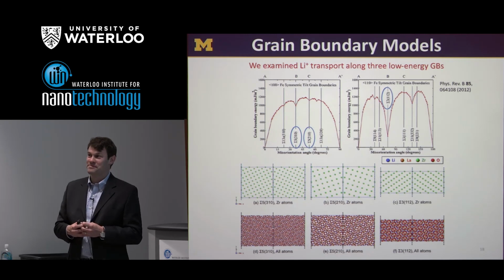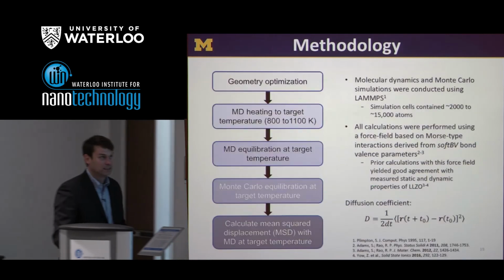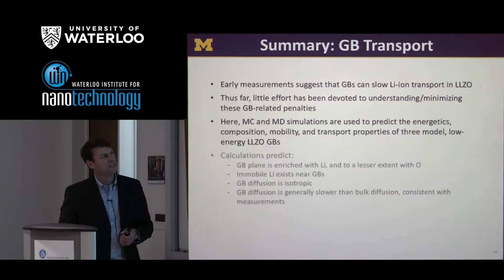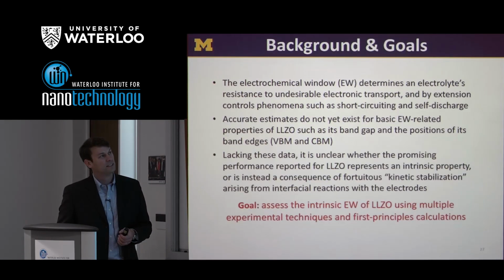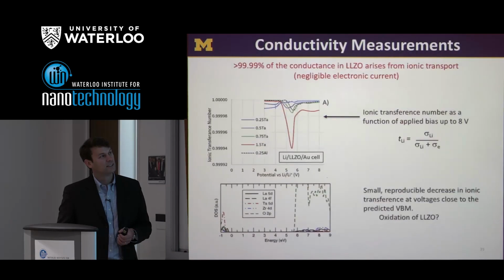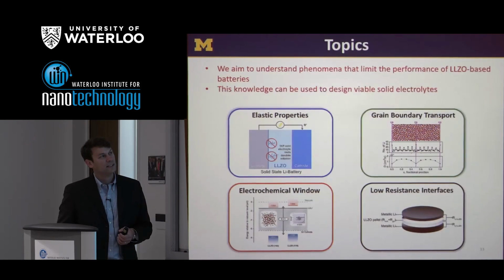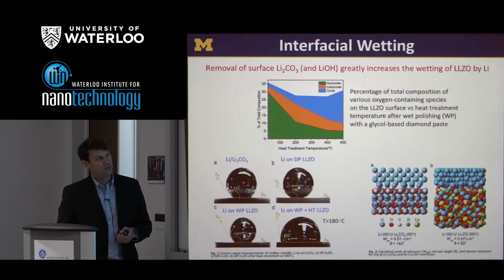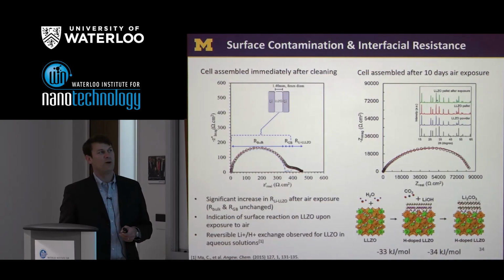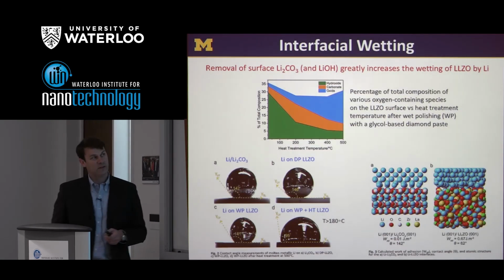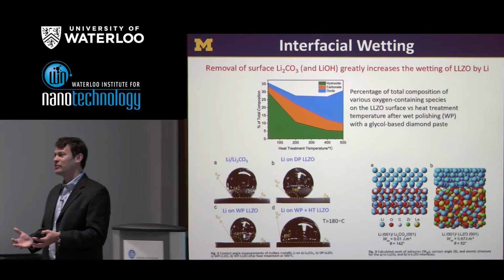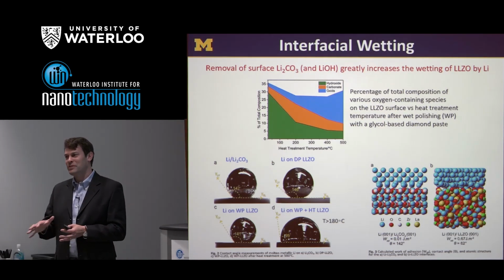About the wet polishing and heating treatment. Question about heat treatment: do you need to heat it under a protective gas atmosphere or just in the air? So I'll tell you what I know about these experiments. All of the polishing in this case is done outside of a glove box, and then after that polishing is done, they stuff it in the glove box right away.